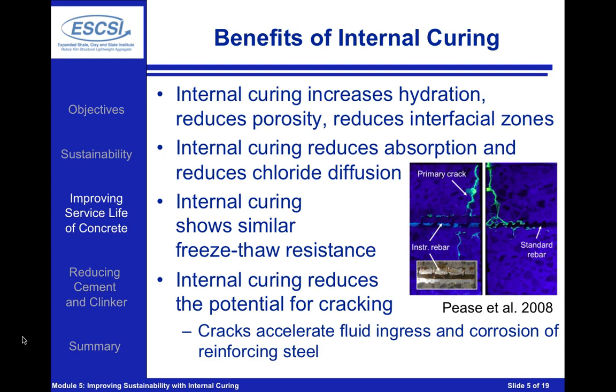So we really see that internal curing is going to work primarily in two ways in terms of improving the overall service life. One, we're going to be able to get more out of the matrix itself because we've reduced the porosity and reduced the connectedness of the interfacial transition zones. But much more importantly, we're going to minimize the potential for cracking. And by reducing that potential for cracking, we're taking out these short circuits that can get the chloride ions right to the reinforcing steel.